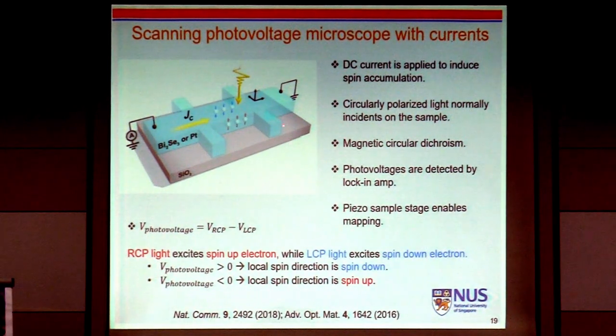So let's say I shine my laser exactly in the middle, and then if I calculate this signal, I will have a zero because I will have equal spin population, so the absorption of light will be the same. Once I move my laser spot to one of the edges, then I now have a preferred spin accumulation. Due to this, it will break the symmetry, so this voltage will not be the same, and then eventually I will have a finite voltage. So depending on spin population, I can have either positive or negative. So this is the principle. Then I have a piezo sample stage, and I can move and image in a two-dimensional form.